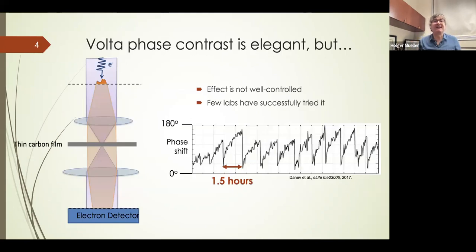Unfortunately, it has been very hard to implement this in electron microscopy. One of the most successful ways to implement it is the so-called Volta phase plate. So here's a very coarse schematic of an electron microscope. Don't take it too seriously, but there is a specimen here. Right after the specimen, we have the exit wave. There's an objective lens, and in the focal plane of the objective lens, I insert a thin carbon film.